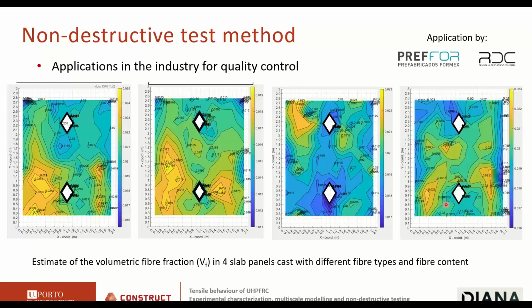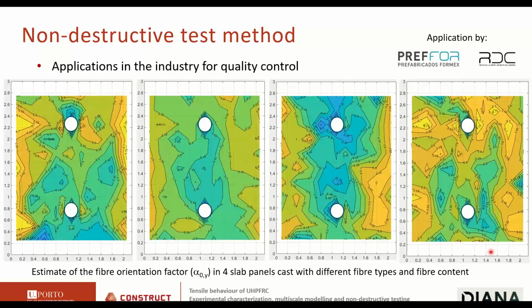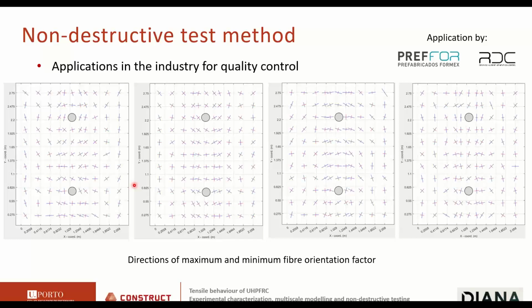Here I show an application by PREFFOR, a precast company in Spain specialized in UHPFRC, which is using this method for quality control of their elements. Here you see the estimate of the volumetric fiber fraction of 4 panels that were cast with different fiber types and fiber content. And the estimate of the fiber orientation factor. Here you don't see values that deviate too much from 0.5, so the orientation of the fibers is really random. And here, the directions of maximum and minimum fiber orientation factor.